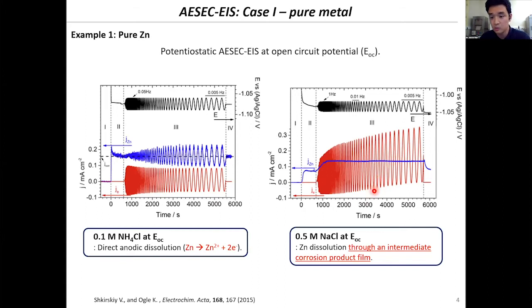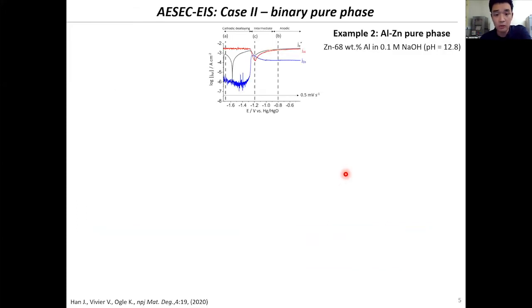So in this case, what was proposed is zinc dissolution occurred through an intermediate corrosion product film, which should be zinc oxide or hydroxide. So we could distinguish different mechanisms of this simple system using this coupling. The other, a little more complex system, which I was working on in Kevin's lab, is a zinc-aluminum binary phase in the alkaline solution.